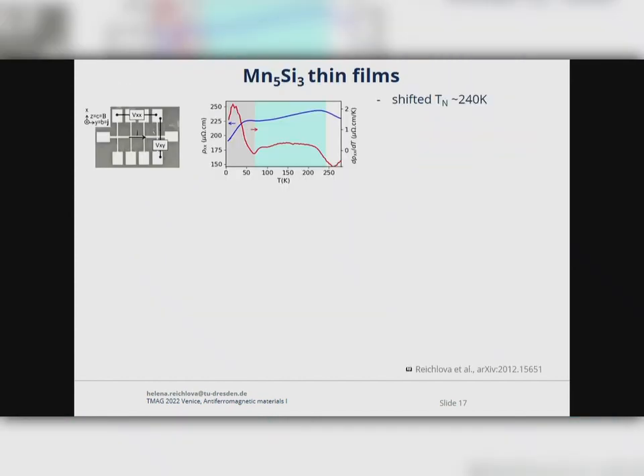So from these films, we fabricated our Hall bars. And it's a standard Hall bar. We apply the current along the main channel and measure the transversal and longitudinal voltage. And we first look at the resistivity as a function of temperature. And from these two kinks, we already see that something is a bit different than for the bulk: the second magnetic transition shifted up to the higher temperature, to this 240 K. The first one stayed at approximately the same temperature.